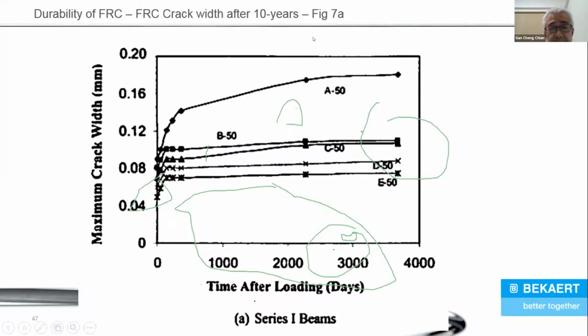FRC crack width after 10 years. So this is crack width. And A again is plain concrete. And B, C, D, E is fiber concrete. B is 0.5% of fiber. So B is 40 kilograms of fiber concrete. C, D, E is higher dosages of fiber concrete. So you can see that in year one, 1994, the crack width for the fiber concrete is about 0.1 actually. And after 10 years of sustained loadings, it's still around 0.1. So it didn't increase. The amount of crack is still at 0.1. But if you look at the plain concrete, the crack width goes beyond 0.1. It's closer to 0.2 after 10 years.